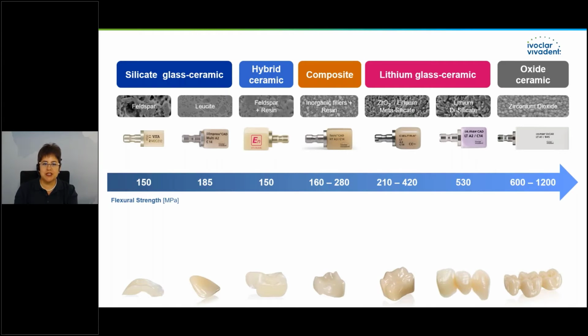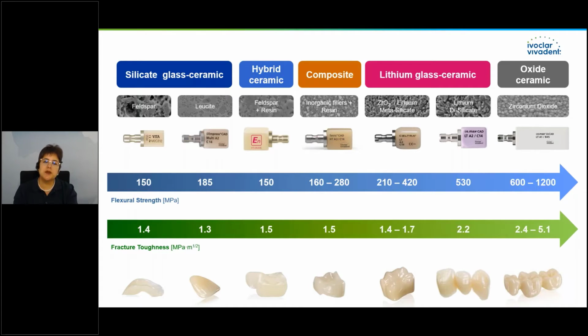Coming back to my previous slide, which of all these materials can be cemented conventionally? Do you know it by heart? There are not so many. You see only 2 materials have a higher fracture toughness than 2. You see here our zirconia and lithium disilicate. And the lithium disilicate has double bonding on the silicates, therefore the di. And here the competitor materials like Celtra or Vita Suprinity have just one bonded silicate. So therefore it is lithium metasilicate. And it is a difference. Therefore, they are not indicated for conventional cementation, but our products are.